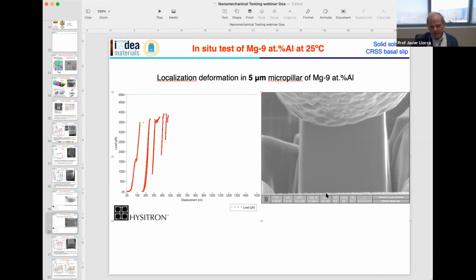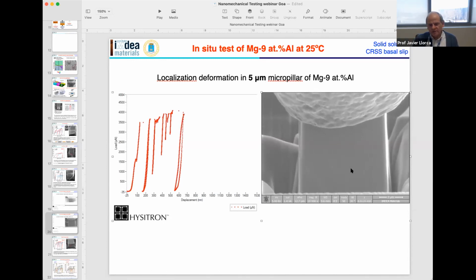Now you can see here this slip band that starts from here, and there are more slip bands. So you can see that the deformation is more homogeneous. As you increase the micropillar dimensions, the deformation is more homogeneous, and you have less localization. And this has to do with the initial number of dislocations that you have in the microstructure of the material.